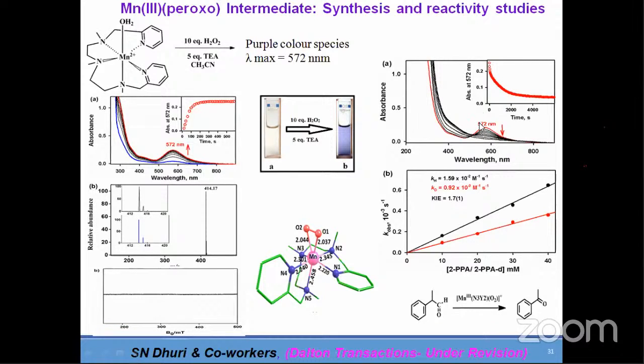Then we did some reactivity with this. We did reactivity with 2-PPA, 2-phenylpropionaldehyde, and also CCA. But CCA was very fast reacting, so we thought of doing only reactivity with the other. There are some reports by Professor Shastri and also Professor Nam saying that the reactivity of manganese peroxide goes via the electrophilic pathway. So we thought of doing that here also. We wanted to know whether our reaction is nucleophilic or electrophilic.